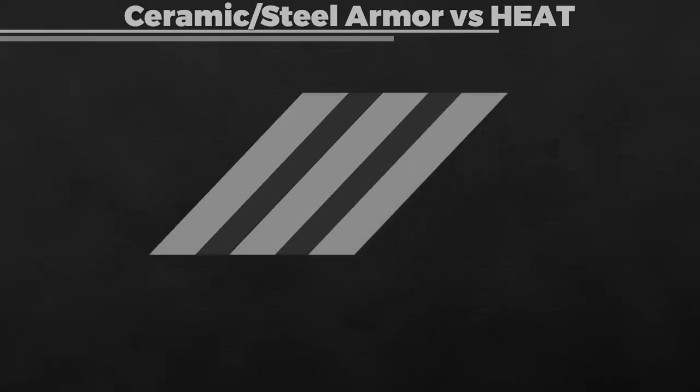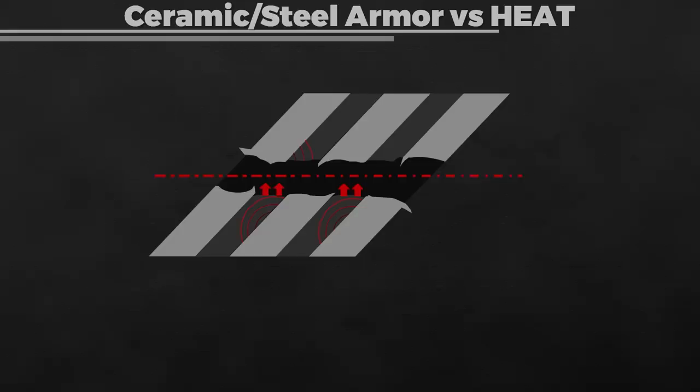How does a multi-layered steel-ceramic armor defeat shaped charge jets? In Professor Held's book, this is described with a composite armor consisting of three layers of steel with two layers of glass in between. The shaped charge penetrates the outer steel layer. Once the jet reaches the interface between the first steel and glass layer, shocks emerge. The shock reflects off the steel layer, and the reflected compression wave results in a reverse movement of the first steel layer, driving some parts into the path of the jet. Simultaneously, fractured parts of the glass layer are also pushed into the jet, resulting in a narrowing of the penetration cavity — repeated with each subsequent layer.